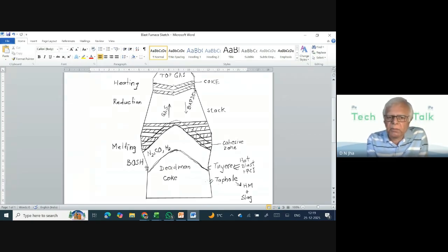So in the Bosh region, this void kind of region that we have, what do we have? Nitrogen. Why nitrogen? Because it is coming from the blast. The common air which has been compressed contains nitrogen, so nitrogen will be there. Then carbon monoxide, because the carbon coming from the coke and the carbon coming from the PCI get oxidized here in the form of carbon monoxide.